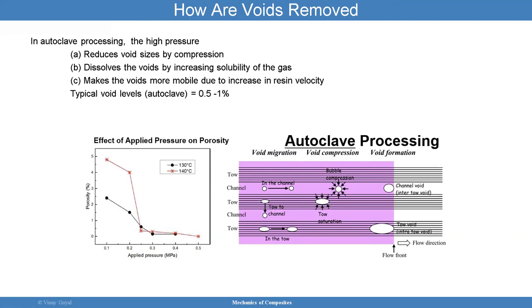How are voids removed? I want to describe this process because it's an interesting process that occurs. In autoclave processing, under high pressure, what we're doing is reducing the void sizes by compression. And it dissolves the voids by increasing solubility of the gas, and makes the voids more mobile due to the increase in resin velocity. The typical void levels from autoclave processes should be in the 0.5% to 1%. If it's more than 1%, there could be an issue with the processing.